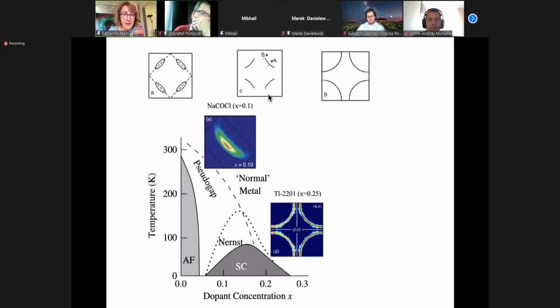It's as if you had taken an eraser and erased part of the Fermi surface in what we call the antinodal region, which is (0, pi) over there. And this is what we call the pseudogap. So the pseudogap opens in the (0, pi) region. It is unusual for theoreticians because we are not used to having Fermi arcs. This breaks the Luttinger sum rule. We are used to counting the number of particles by the volume of the Fermi surface, and here we don't have a volume.